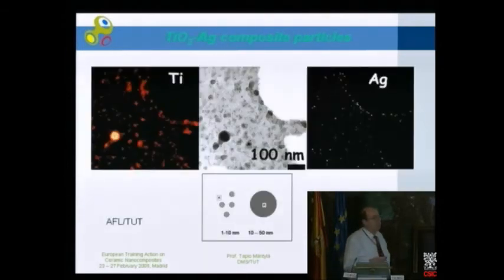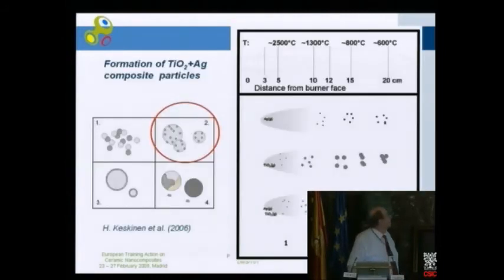And what we have also done, because photocatalytic coating is antibacterial only in UV light, is make a mixture where we have silver and titanium nanoparticles, and we hope to get the coating to be antibacterial also when we don't have UV light. And here are these anatase particles. They are small ones, and there are some droplets formed of rutile particles, and then silver inside the material. And the structure is where we have this titania, and then we have these metallic nanoparticles on the surface of that.